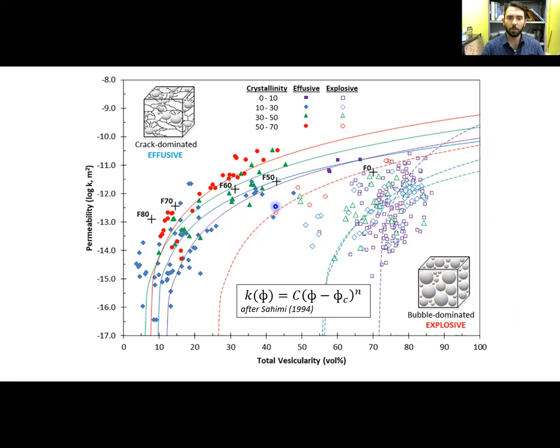Our experiments also corroborate recent vesiculation studies in that increasing crystal fraction reduces percolation thresholds. We can also see this reflected in the natural explosive data, which sees a decrease from 0.7 for crystal poor samples to 0.25 for crystal-rich samples. However, previous studies have only tested vesiculated permeability for crystal fractions up to 0.4.